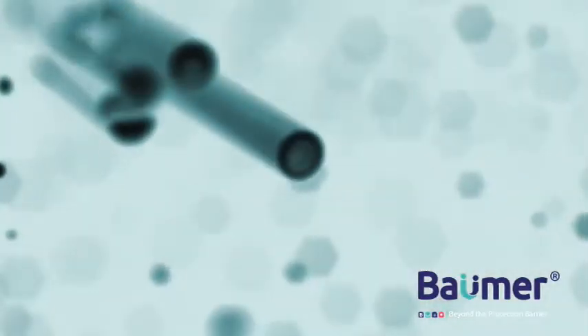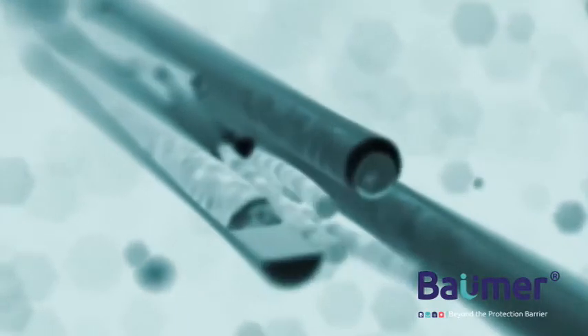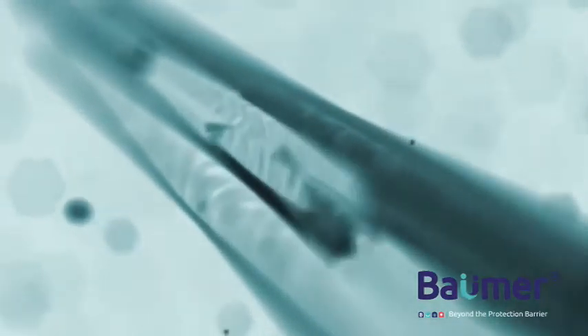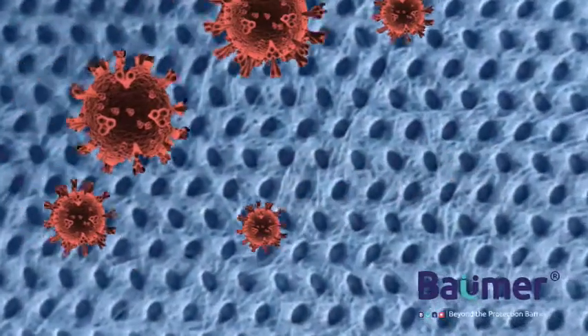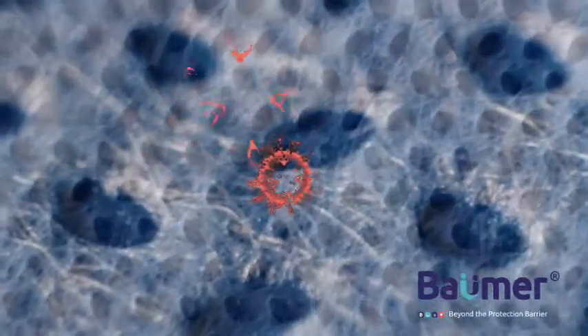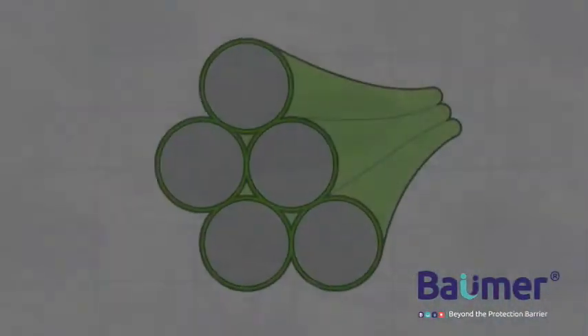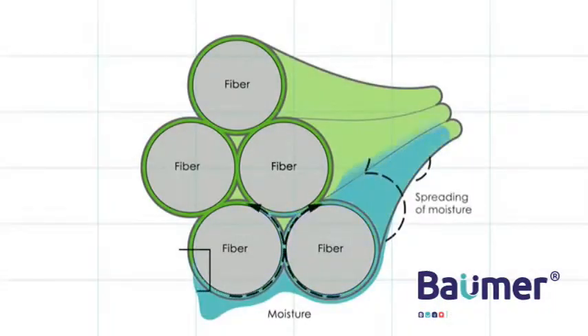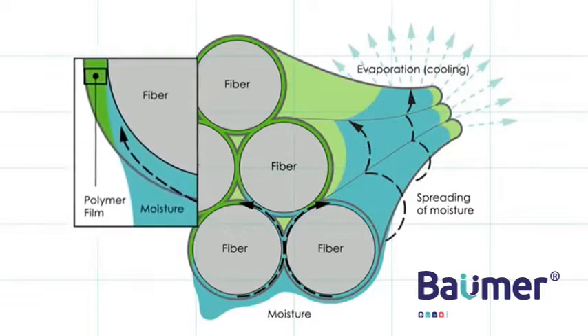Electrospinning uses electrostatic and mechanical forces to obtain nanofibers, from which our nanotextiles are then made, with improved characteristics and new high-performance properties as a protective barrier against pathogens. Our nanofibrous fabrics are made up of at least one layer of nanofibers, containing at least 60% modified polyethylene nanofibers with a molecular weight of 70,000 to 110,000 daltons.